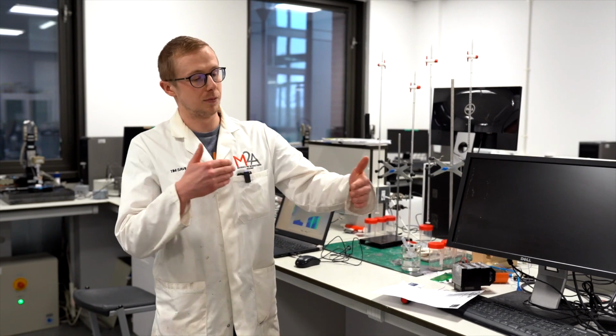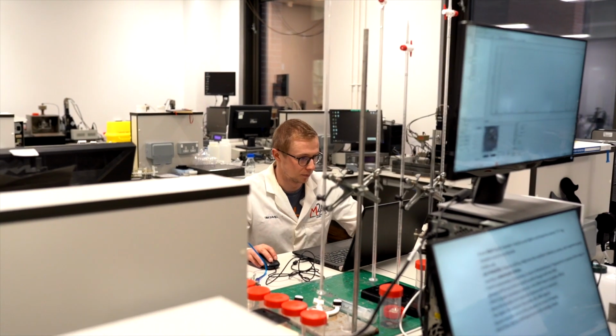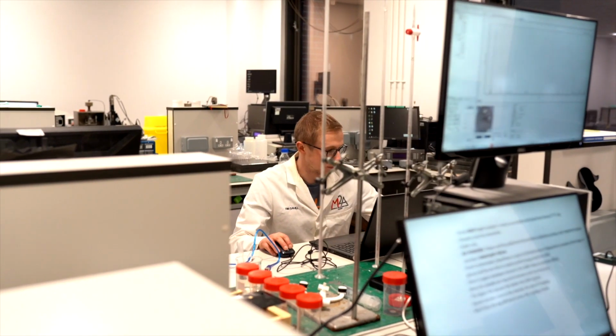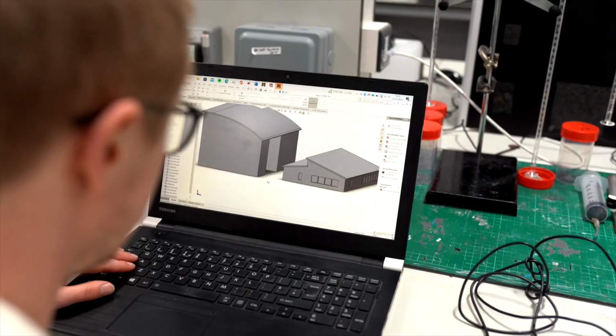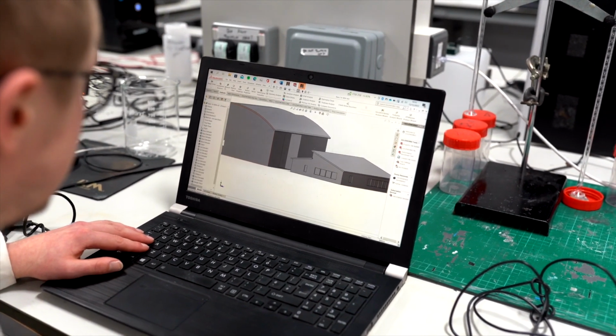Some of the key things I've looked at are RFID based sensors, so they offer a reasonable range of detection, and they would allow a semi-remote autonomous method of detecting the corrosion. Other methods I've looked at are embedding thin electrical sensors between the coating layers, and these can detect things such as water uptake into the coating as well as blistering.